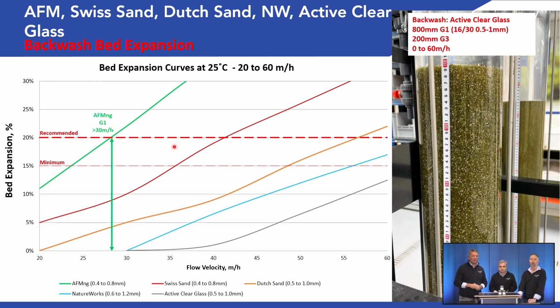Mike, do you bring us through this? Sure. With the AFM-NG, because of its hydrophobicity, it's slightly lighter than many of the other medias, including our AFM standard. So it reaches 20% bed expansion at 30 meters per hour backwash velocity, and really good fluidization. What would be AFM standard? AFM standard, we're looking at slightly higher. Our recommendation is 40 meters per hour at minimum.